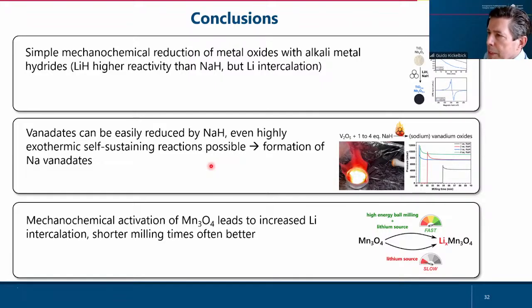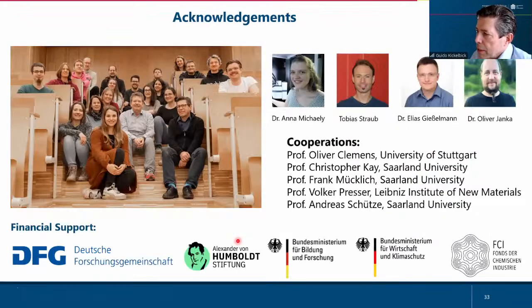So you have seen that simple mechanochemical reduction of metal oxides with alkali metal hydrides is possible. I have shown you that the production of vanadates by mixing vanadium oxides and sodium hydride in the mill is a very easy way to do this intercalation and at the same time the reduction. And in the last point, I have shown you that activation of manganese oxides can increase the lithium intercalation, which is a potential way to get better, more activated battery materials.